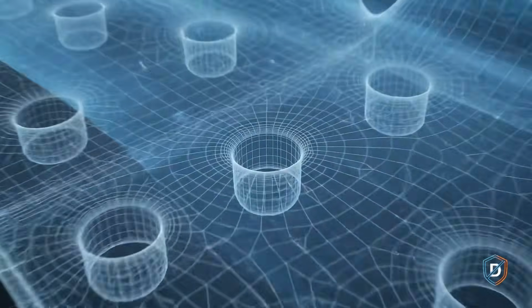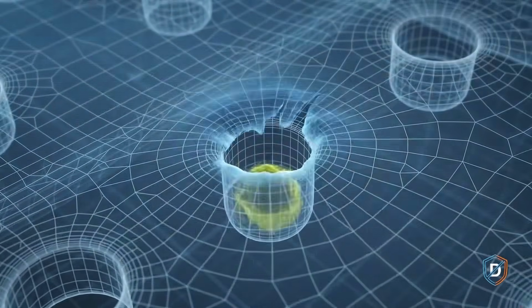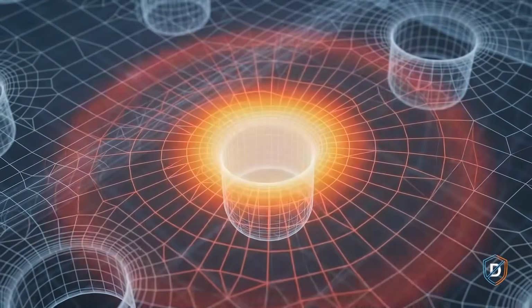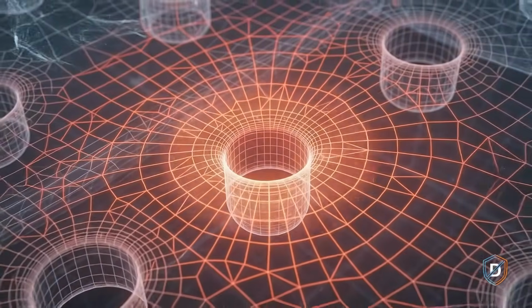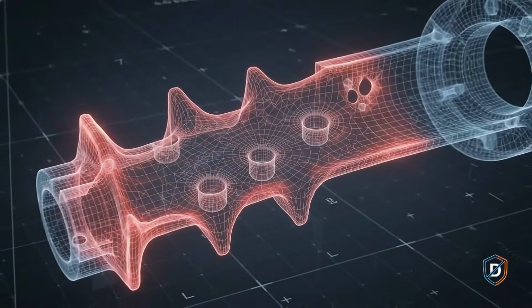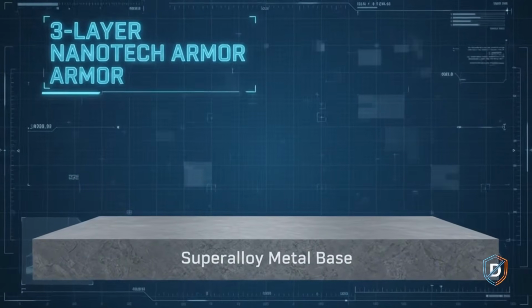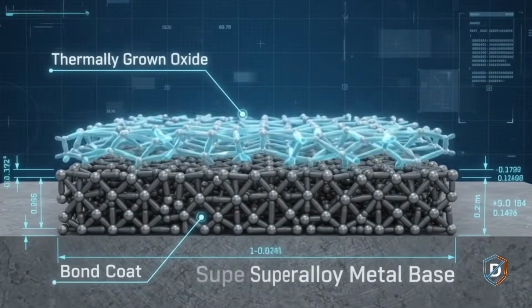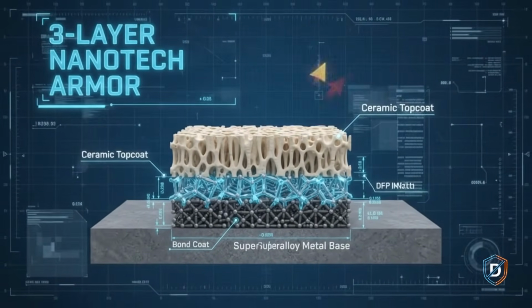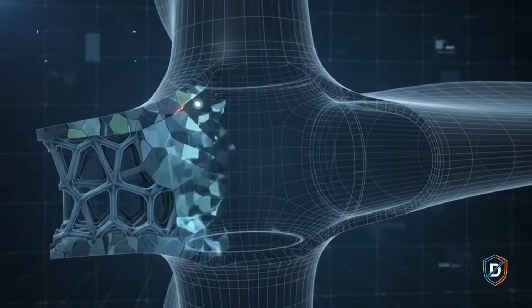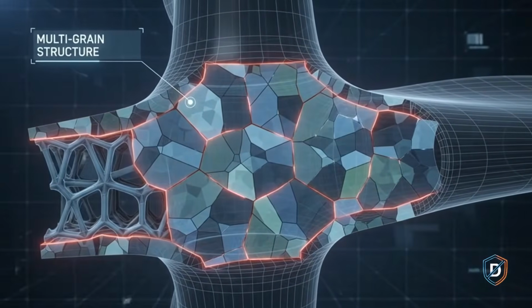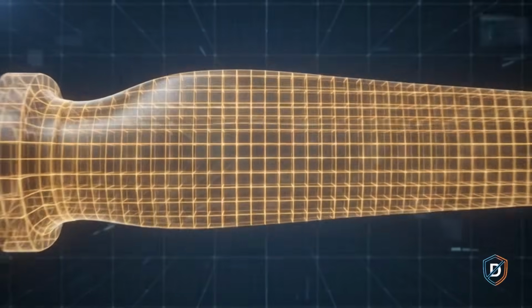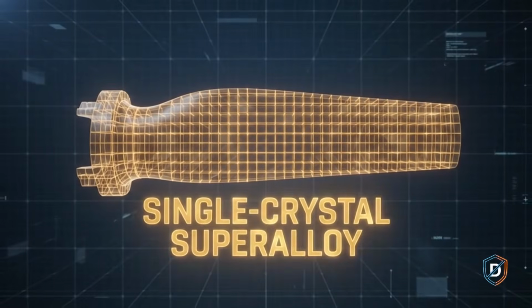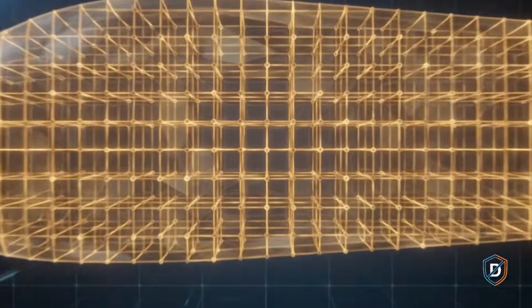If a single cooling hole clogs, the cold air blanket ruptures, a localized hotspot forms, and structural decay begins in less than 50 milliseconds. Because film cooling can fail, engineers coat the metal in a ceramic barrier so advanced it requires 3 distinct microscopic layers to stay glued to the alloy. Underneath the ceramic lies metallurgy's greatest secret. The entire turbine blade is grown as one single, continuous metal crystal.